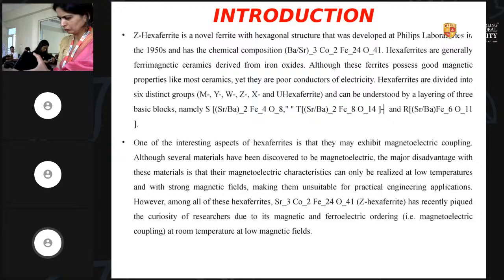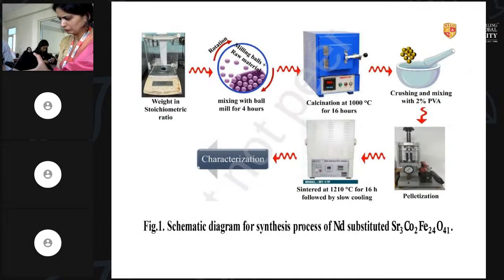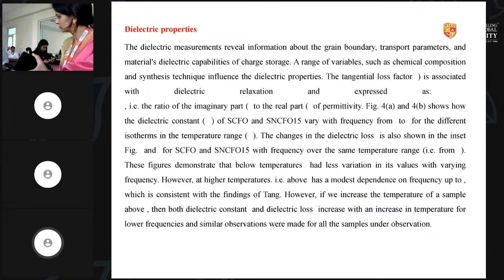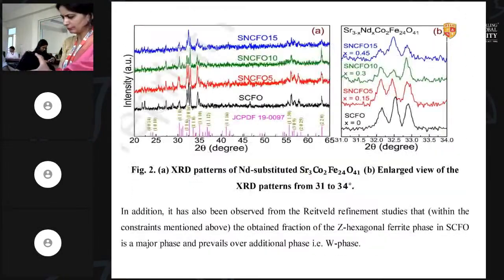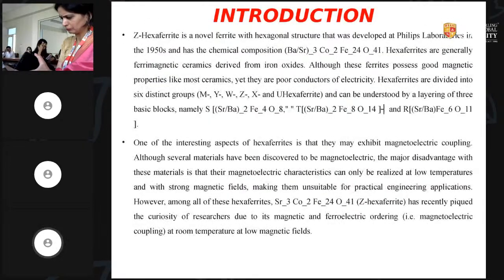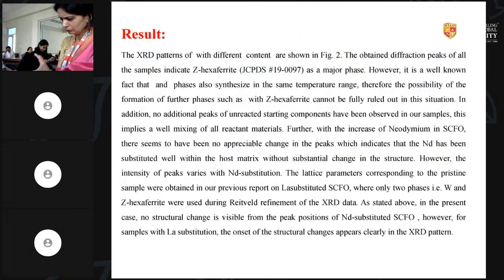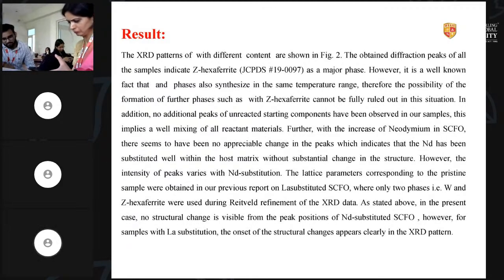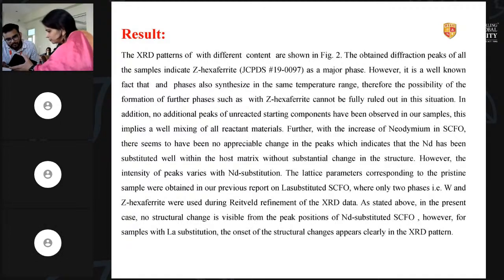Now scanning electron microscopy. The SEM micrographs are shown in figure 3A to D. No foreign particle or impurity seemed to be visible from these micrographs. It is relevant to mention that a slow cooling rate during synthesis has improved the grain size of all the samples and the grain boundaries are not distinct. Therefore, it is very challenging to find the specific grain size of the prepared samples. Besides, it is quite visible from this SEM image that the prepared samples are denser with less porosity.